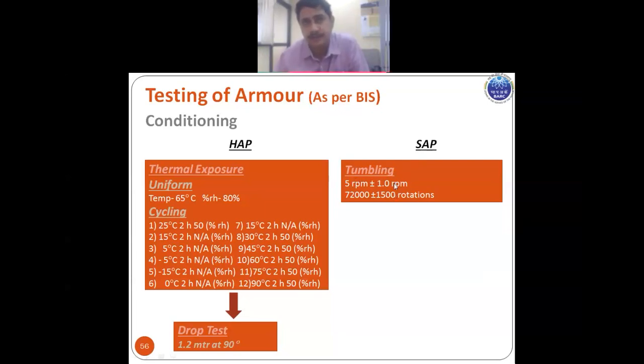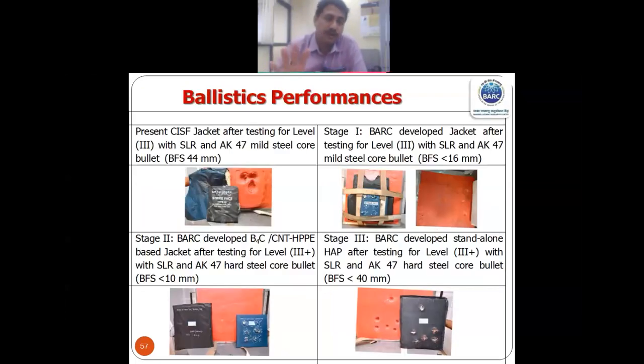The tumbling is happening under water, a drum containing water that rotates for 10 days at a particular RPM. So the soft armor panels are kept under that. After doing all this tumbling and thermal cycling, then the ballistic test is done. That means the bulletproof jacket has to withstand this harsh atmosphere. So now I am showing some of the results, glimpses.